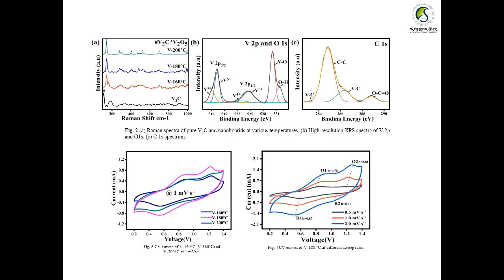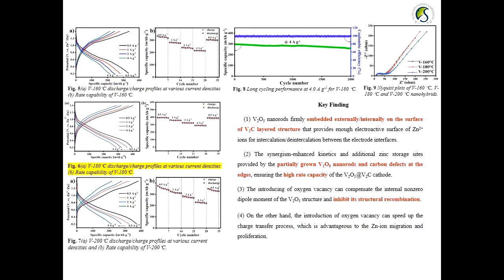Further, we varied the current with 0.5, 1 and 2 for the 180 degrees centigrade sample at different sweep rates, compared with 160 and 200 degrees centigrade. With it, I can clearly see that at 180 degrees centigrade, the rate performance was more stable when compared to 200 degrees centigrade.